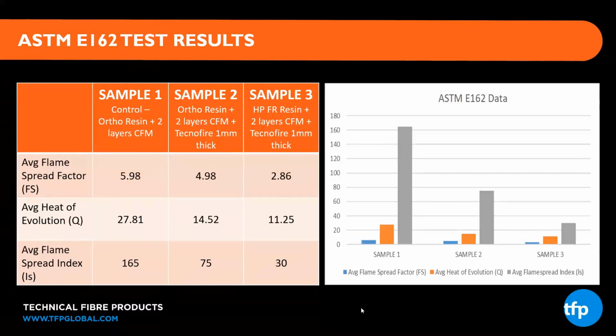So very commonly in construction, architecture, trains, there are panel systems. So we've looked at trying to design a market-led panel, a generic panel for the industries to look at. And we've chosen 3 different samples to run where you can see how we've increased the fire retardancy from sample 1 to sample 3. Sample 1 was the standard industry ortho resin, 2 layers of a continuous filament mat, a glass mat. In sample 2, we added a 1 millimeter Tecnofire that does contain the ATH powder. And in sample 3, we went with a high performance flame retardant resin, plus those other layers already mentioned. So we've scaled up in complexity from sample 1 to sample 3.